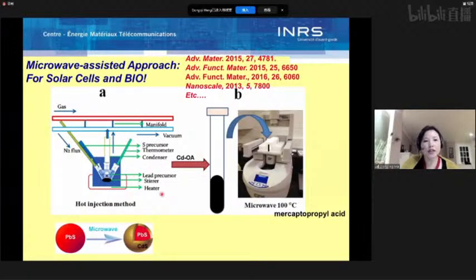For near-infrared quantum dots, we developed a microwave-assisted approach for large-scale, high-yield synthesis. We started with lead sulfide quantum dots, then we put a cadmium sulfide shell on by the microwave approach, and this shell can help increase photoluminescence properties and also stability, and the quantum dots can be well dispersed in an organic phase.